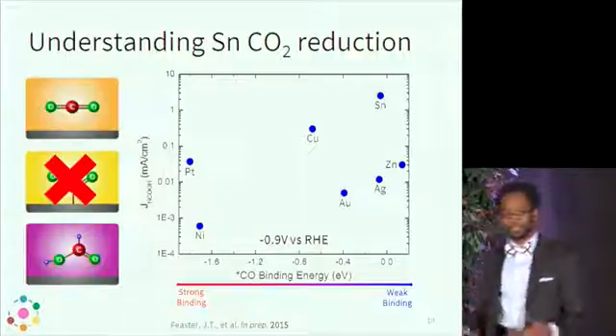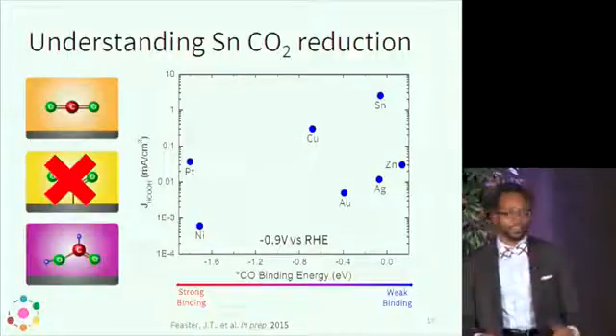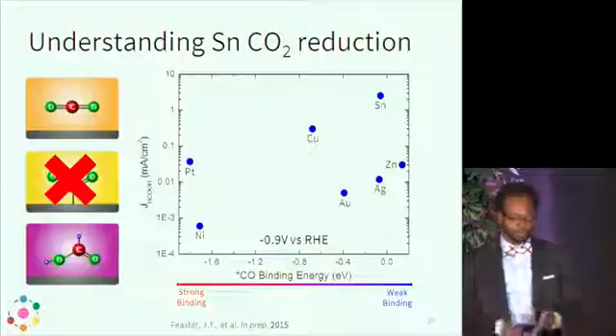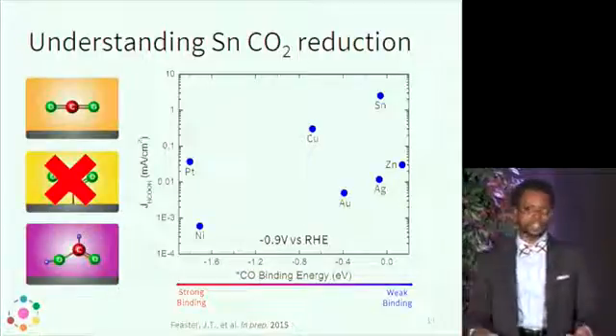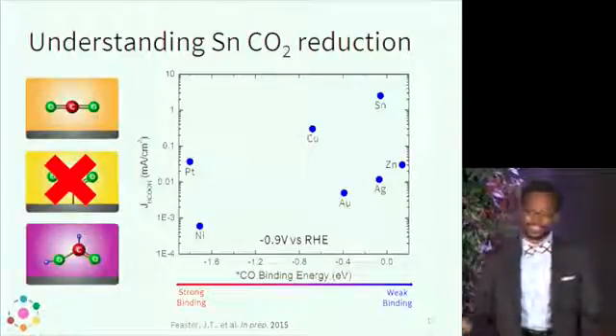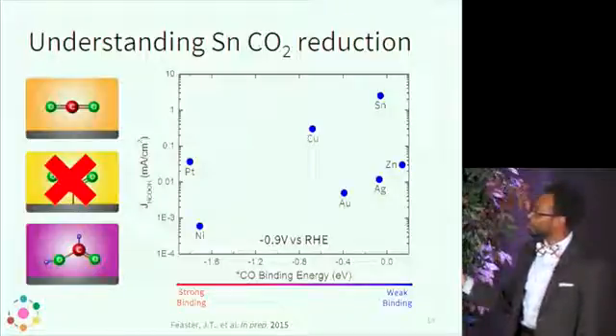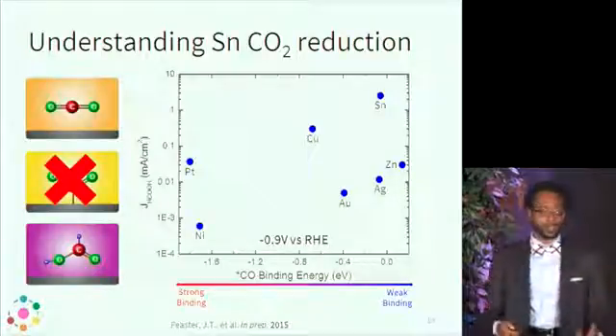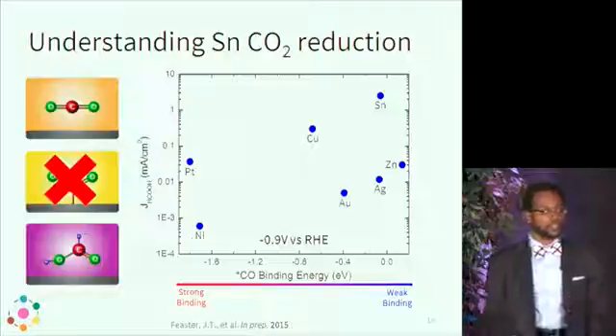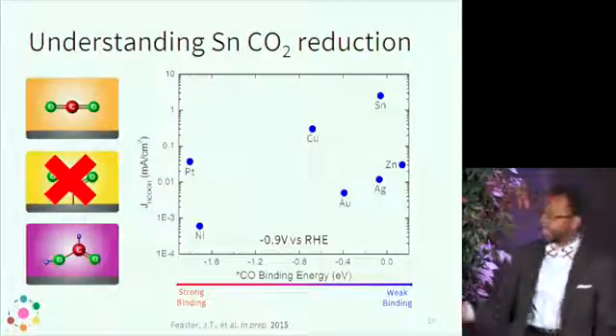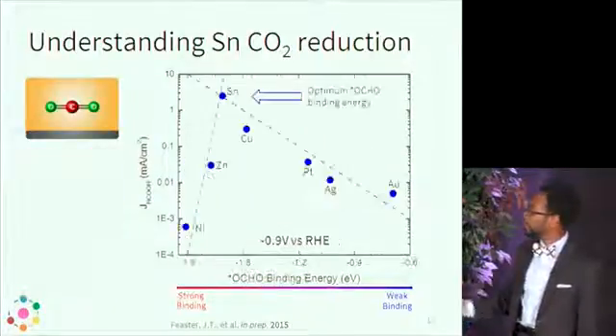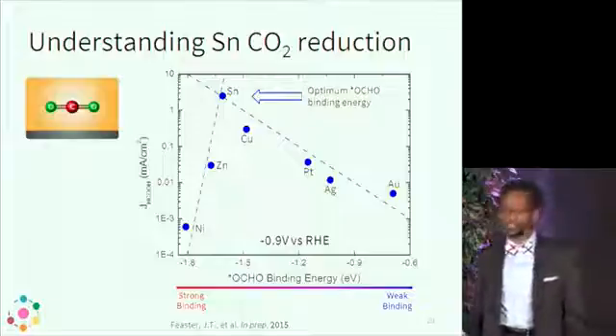So we kind of took a step back, thought about it, and of course, just made the problem as simple as possible. Carbon dioxide has 3 atoms. It has a carbon, and it has 2 oxygens. So if we were to look at the oxygen binding energies and see how that correlates to formic acid production, maybe we can then capture our volcano trend again, and that's exactly what we're able to see.